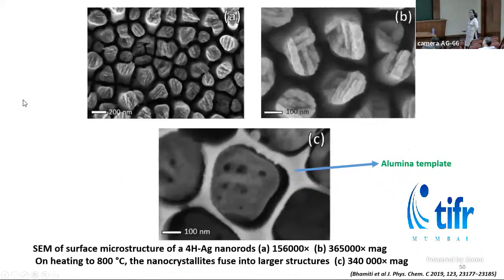Now seeing is believing. Can we see this in SEM? These 4H silver nanowires have a typical bamboo-like surface morphology, which can be clearly seen in this image. When this nanowire sample was heated, this bamboo-like morphology disappears, and we can see these flat images of the wire. These were heated in the alumina template itself.